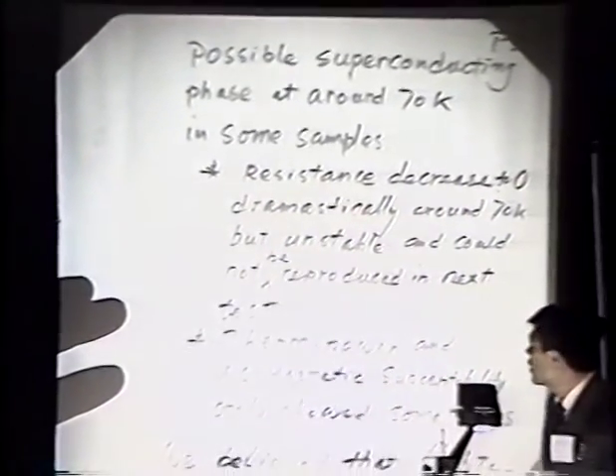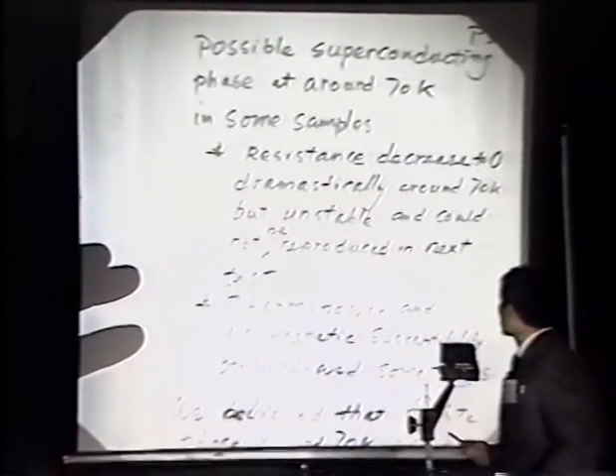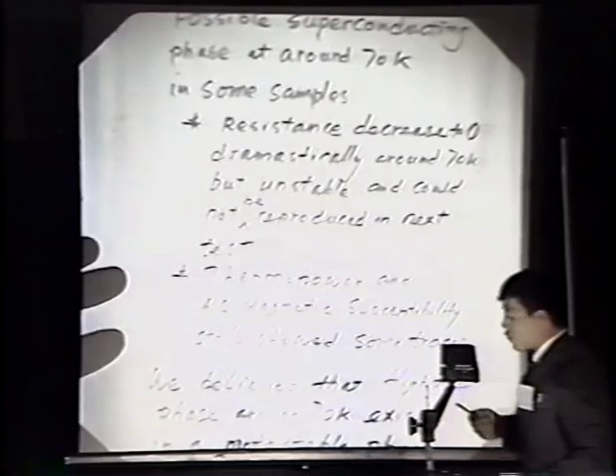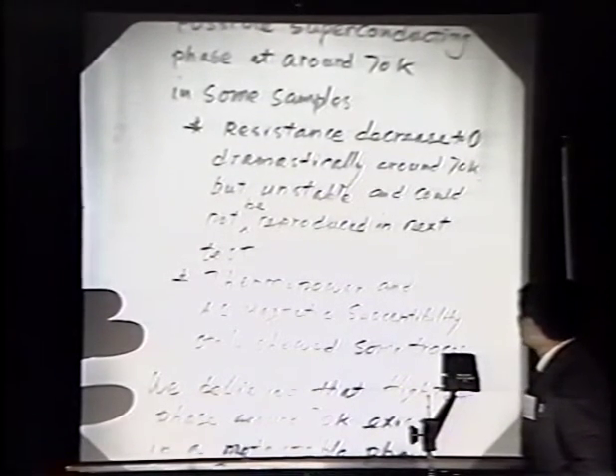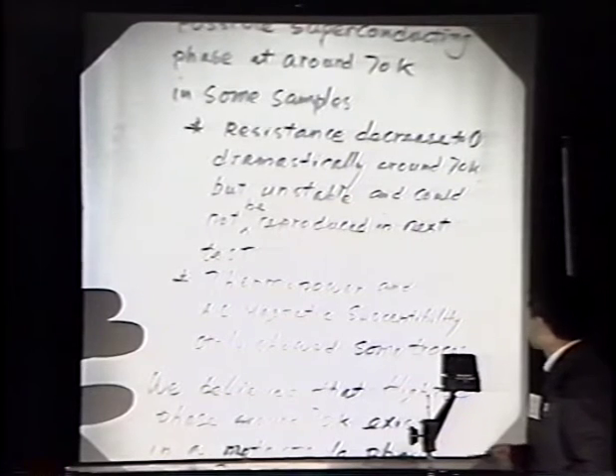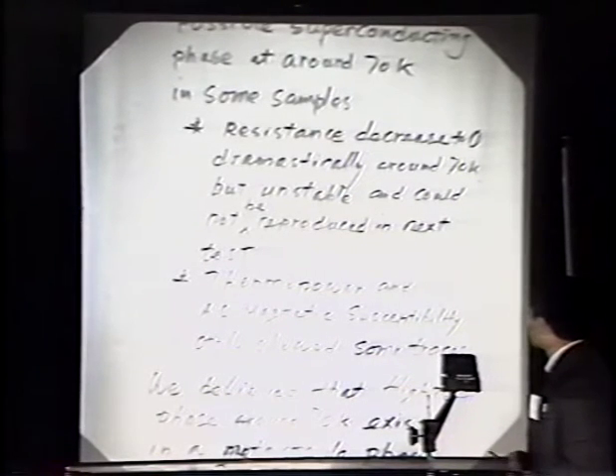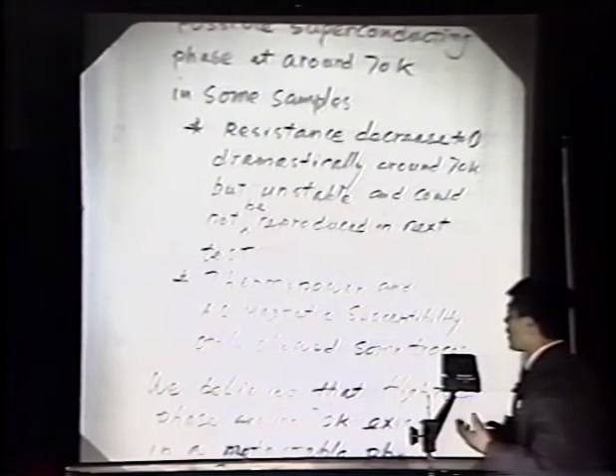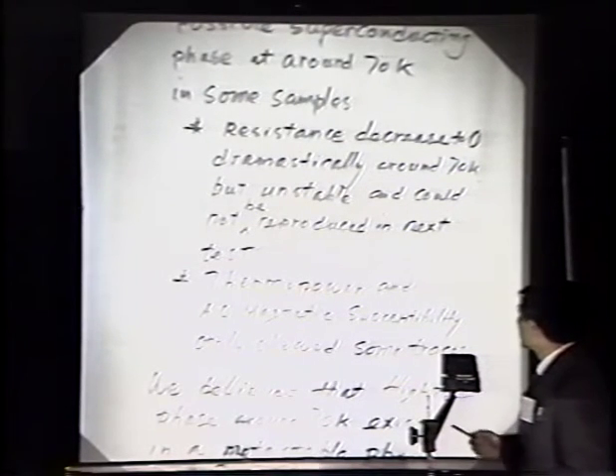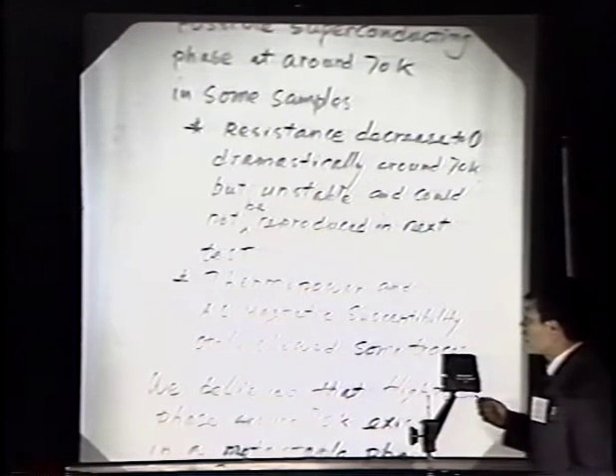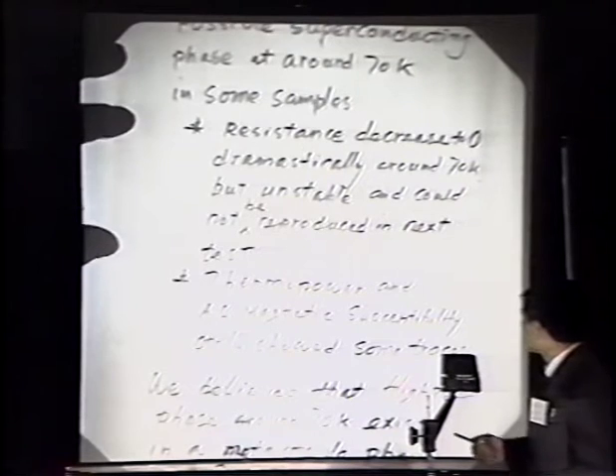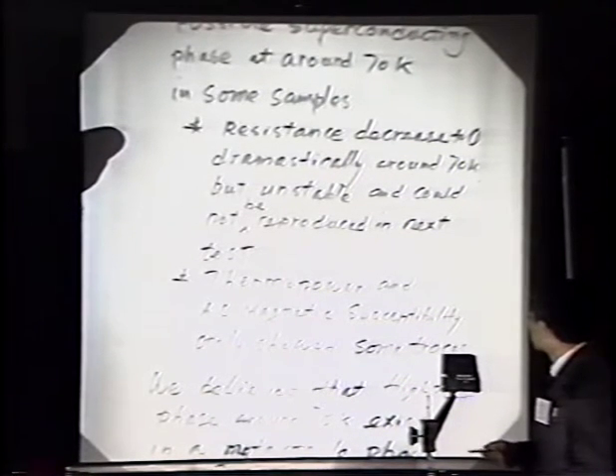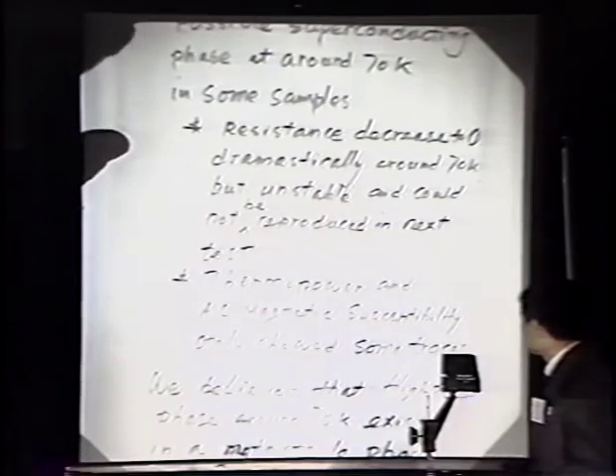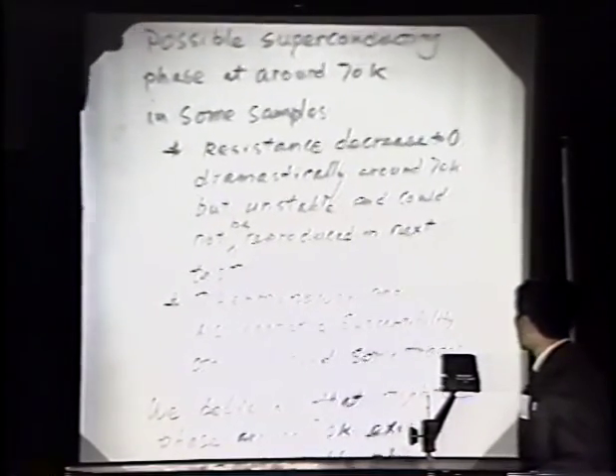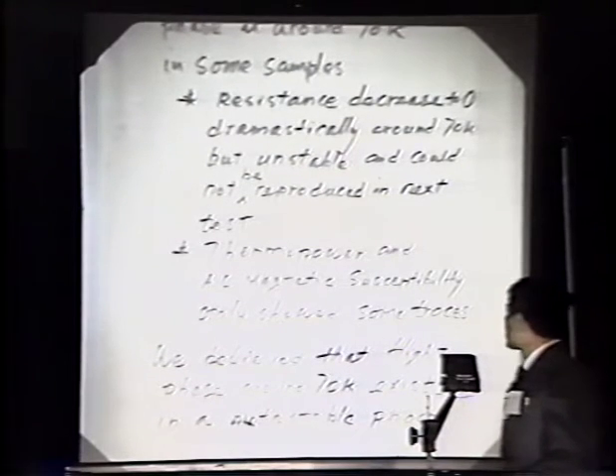Probable superconductivity at around 70 K in some samples we have observed, for the following reasons. One is resistance decreasing to 0 dramatically around 70 K, but this phase is unstable and couldn't be reproduced in the next test. As I mentioned above, the sample with TC of 48.6 K is a little bit stable, but this one is very unstable. And the thermopower I have shown you, and the AC magnetic susceptibility only showed some traces. For this reason, I believe that the high TC phase around 70 K exists as a metastable phase.